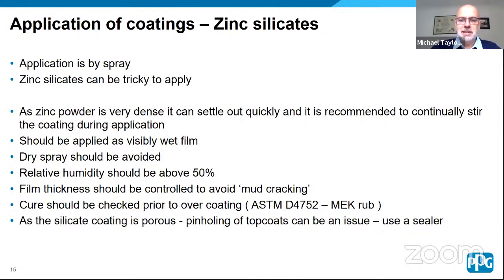This is done with the ASTM D4752 MEK, methyl ethyl ketone, rub test. It's basically you put the solvent onto a rag and you do 50 double rubs and check how much of the rag is discoloured by the zinc coating. It's important to do it before you overcoat it, because once you put a top coat over the zinc silicate, it's no longer going to have the humidity to allow the cure to go to completion.